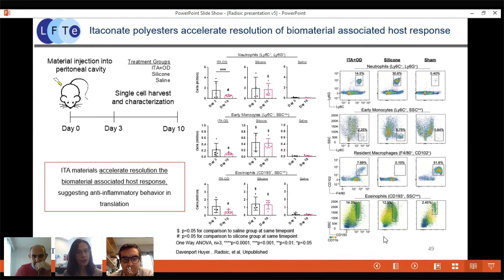And then at 2 time points, he measured the presence of neutrophils, early monocytes, and eosinophils in the peritoneal cavity. And this is possible by rinsing and harvesting all cells from the peritoneal cavity. And as you can see here, in all of these cell types, with time, there is a very rapid resolution of inflammatory response with itaconate, and the inflammatory response persists with silicone. Looking back at these data, it is really not possible to prevent inflammatory response from occurring fully. But what we want to see in a biomaterial is that it does resolve quickly and that it does not persist for a long time. And through Locke's work here, we demonstrate that itaconate-containing polymers are capable of giving us that functionality.